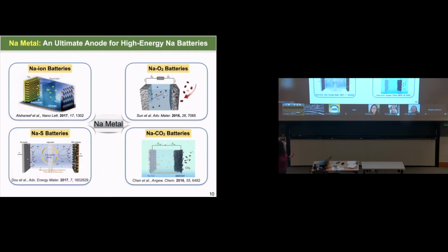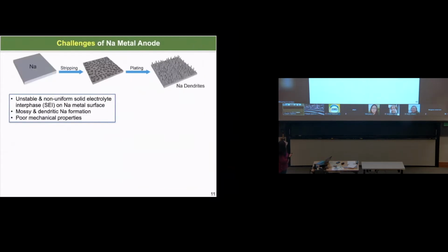energy sodium-based battery system. But if we look at the sodium metal anode, why hasn't it really been commercialized, and why is this anode still considered a dangerous anode material to be used in different types of sodium batteries? The main reason is that even though the sodium metal anode can provide a much higher capacity and a low electrochemical potential versus all the different cathode materials, however, during what we call the stripping and plating process, you can translate the stripping process to a discharging process for the battery, and the plating process is the charging process for the battery system.